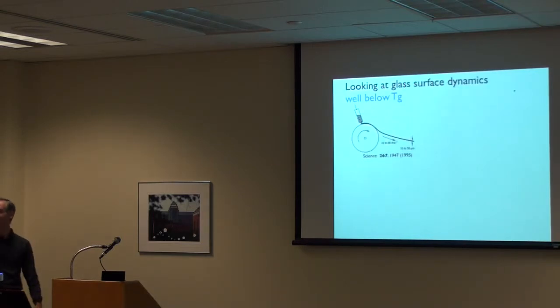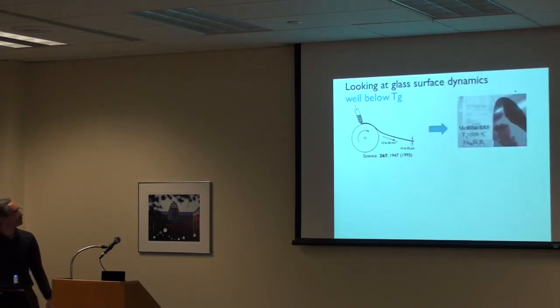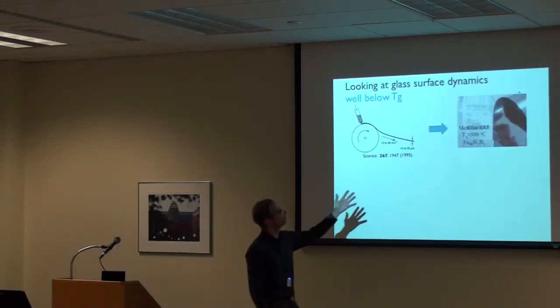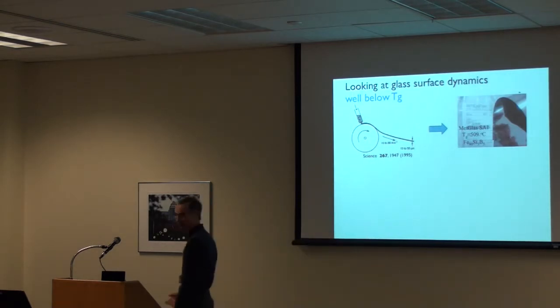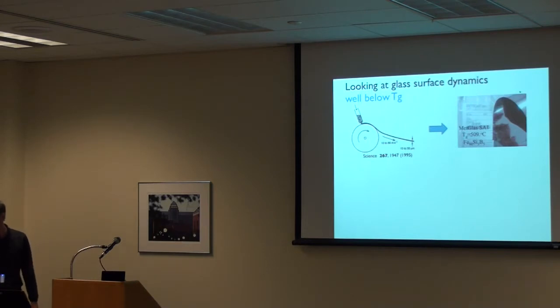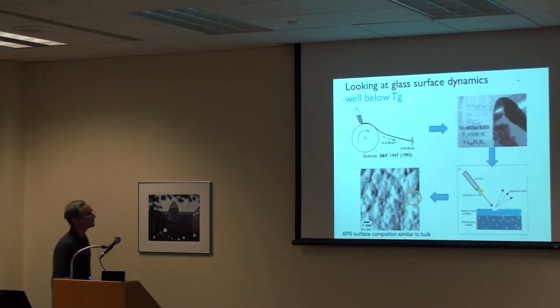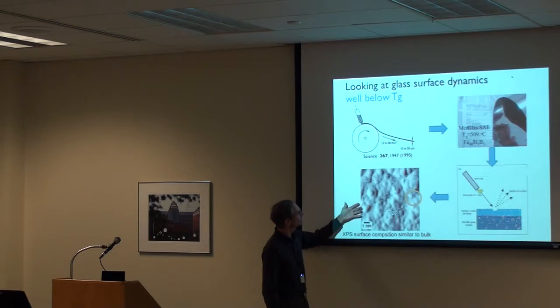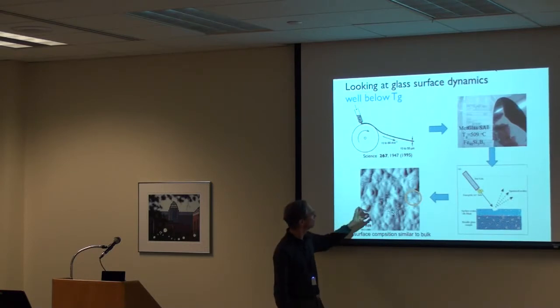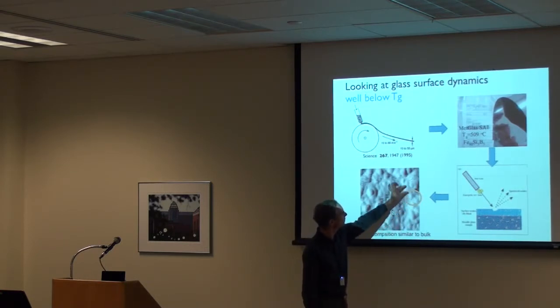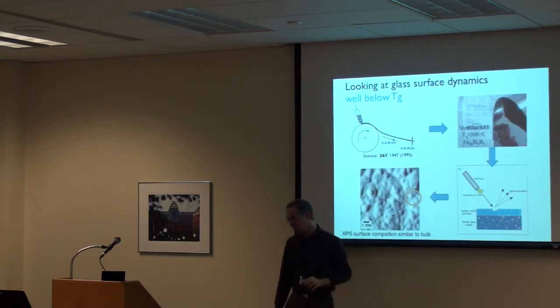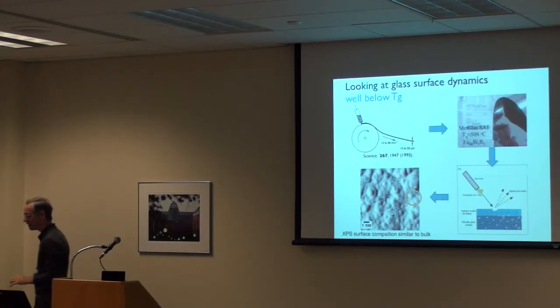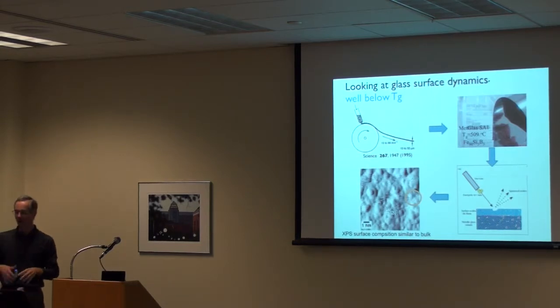So Sumit Ashtekar, who's sitting somewhere there in the back of the audience, did experiments where we basically took metal glasses. It turns out you can actually freeze metals fast, some metals anyway, fast enough to make glasses out of them and make glassy films. And he cleaned off the oxides on the surface of these films in UHV and looked at the surfaces. And so you end up with something that looks like this. It's this sort of lumpy, corrugated-looking surface, no extensive long-range order on there. And if you look at it, there's sort of a length scale of lumps that you see in various places on this surface. And it turns out that length scale is, in fact, approximately five atoms in diameter.